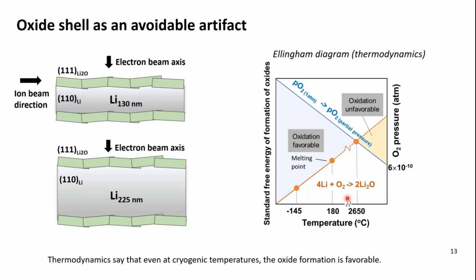According to the calculations, the oxidation is possible if the temperature is below 2,650 Celsius. Of course, this is under the assumption that lithium exists as a solid at such temperature, and actually it will melt beyond 180 Celsius. However, what we're interested in are temperatures close to cryogenic temperatures, so our assumption is still pretty accurate. And at cryogenic temperatures, based on this calculation, the oxidation is always favorable. So that's why we can see some lithium oxide, because of the lithium oxide reaction.